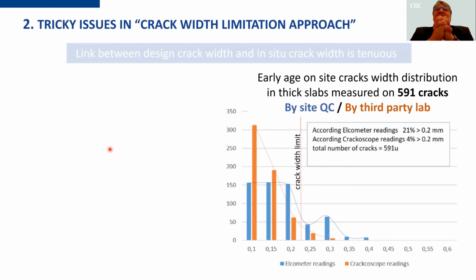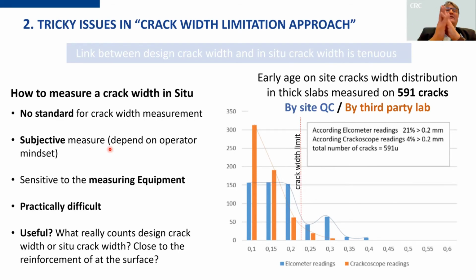Now, the link between calculated crack width and in situ crack width is more or less tenuous. And also, it is very difficult to measure. Why? Because first, there are no standards to measure the crack in situ, which is a subjective measure, which depends on the mindset of the person who takes the measure. It's sensitive to the measuring equipment. It's not easy to do. And in fact, is it useful? But the problem is that with a contract, with the client, if you have large cracks, your structure is bad. You worked badly. It's a problem.